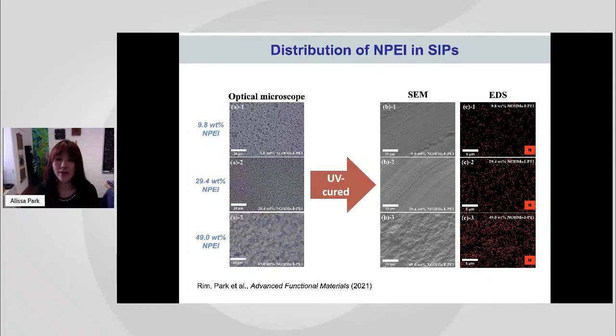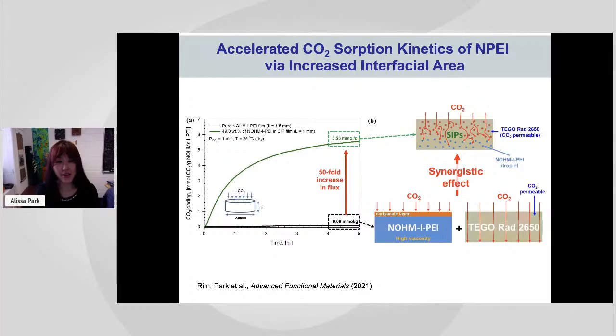And we wanted to see the distribution of these NOHMs, and NOHMs has nitrogen groups, amine groups, so that you can do nitrogen mapping on the right. It was really well distributed. And we were able to see that there's a huge increase in CO2 uptake.